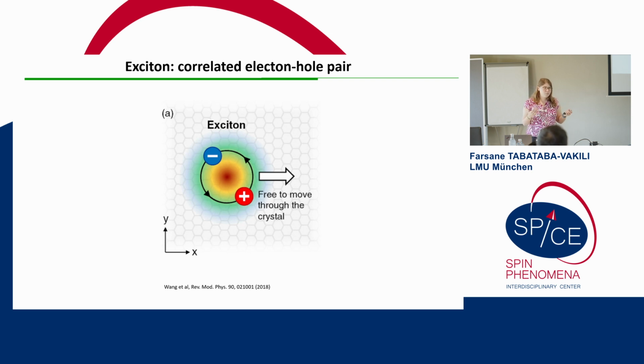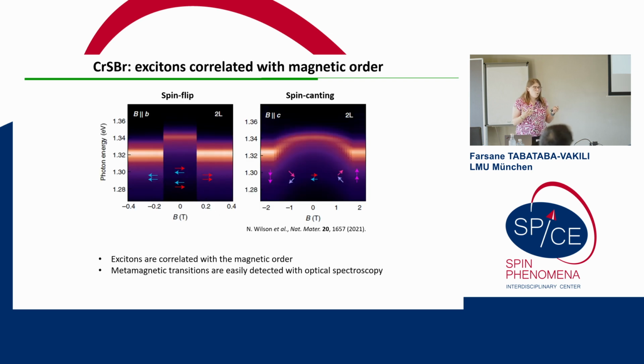So we are optical spectroscopists. We care about excitons. Excitons are correlated electron-hole pairs. They're of van der Waals type, so that means they're quite large with respect to the lattice structure. And so one thing that for us is very cool about CrSBr is that the excitons are correlated with the magnetic order. So this was nicely shown in this work by Nathan Wilson and co-workers from a few years ago, back when he was with Xiaodong Xu.